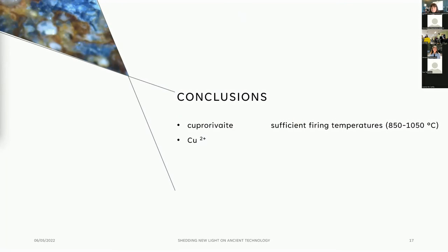Moreover, the fact that we have predominantly bivalent copper compounds in our samples points to an oxidizing atmosphere while firing, and therefore the hypothesis that a reducing atmosphere would disturb the production process was not validated.